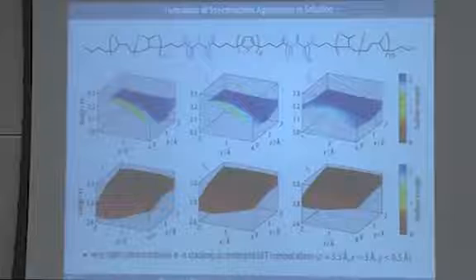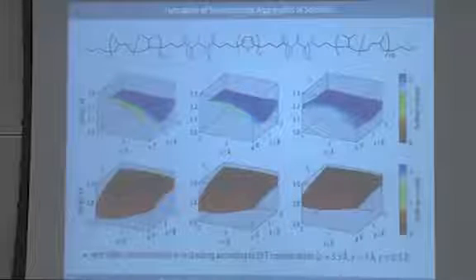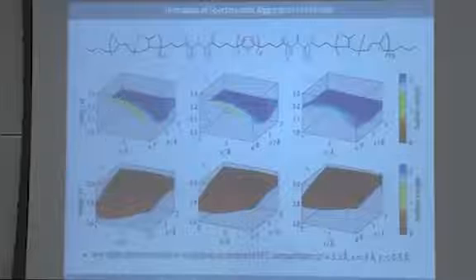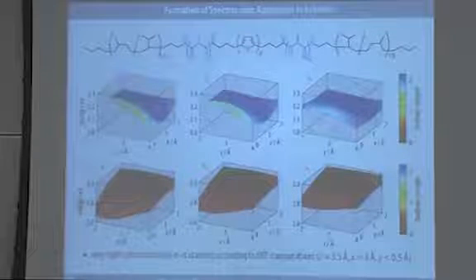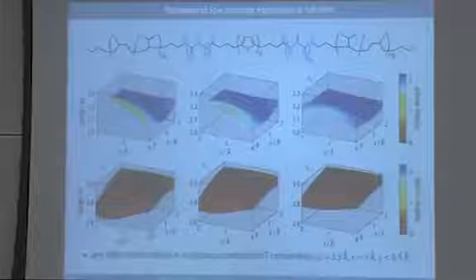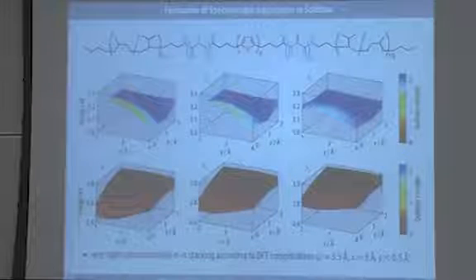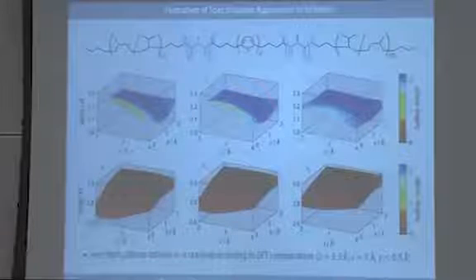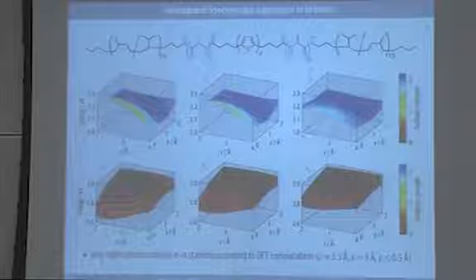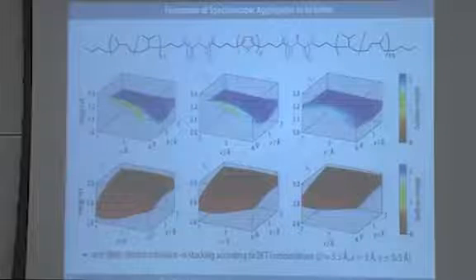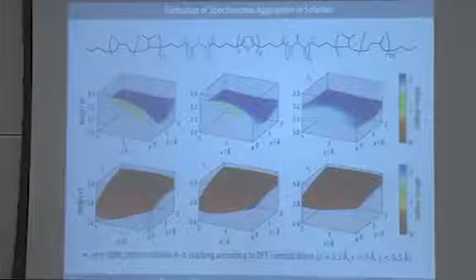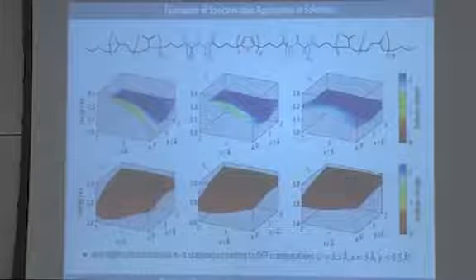angstroms. So this coincides very well with our X-ray determinations, and with a longitudinal displacement on the order of 2.5 angstroms, that's roughly one thiophene ring, and a lateral displacement that is pretty much non-existent, that is negligible. So in terms of lateral displacement, we have an almost cofacial stacking with a bit of longitudinal displacement at a very tight pi-pi stacking distance of 3.5 angstroms.